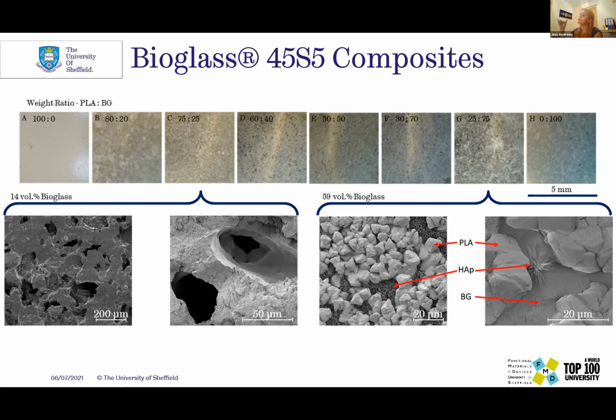And on the right hand side, two images show about 60 volume percent bioglass. You can see two distinct regions begin to occur: a structure of the PLA, and in between that, the bioglass. We've also got some really interesting features in that we think we've got hydroxyapatite beginning to form during cold sintering, which is really good because it shows we're still quite bioactive, since that's the last step in those first 5 that I talked about in the reaction with the body once we've implanted our sample.